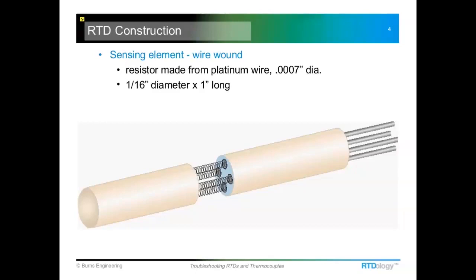So first off, the RTD, resistance temperature detector construction. This is what we call a wire wound sensor. It's one of the more common styles. It's a ceramic tube, and we make little coils of platinum wire and thread them inside the tube, and attach some external lead wires. The internal wires are 7/10,000 of an inch in diameter, so as you can imagine, they're fairly fragile. They have to be supported somewhat so that during shock and vibration they're not moving around too much. But if they're tied down too much, that can put extra strain in that wire and cause a resistance shift. So it's a fine balance between durability and performance of that sensing element.